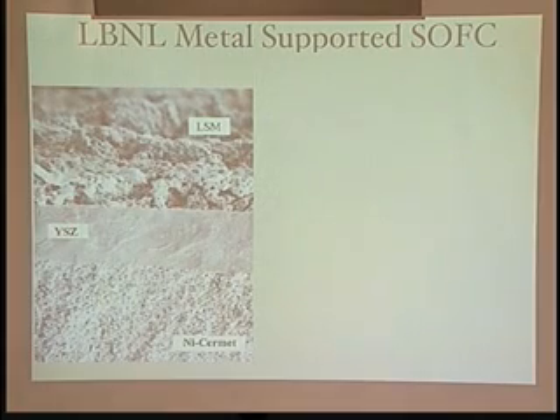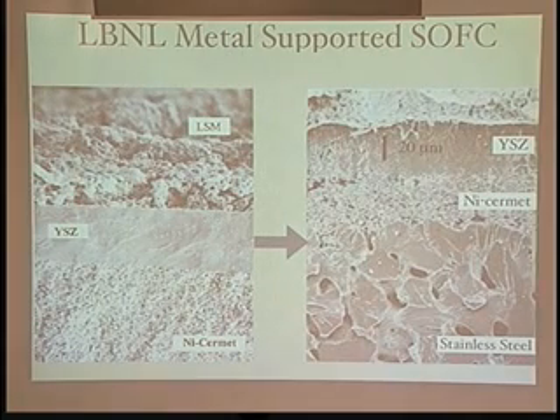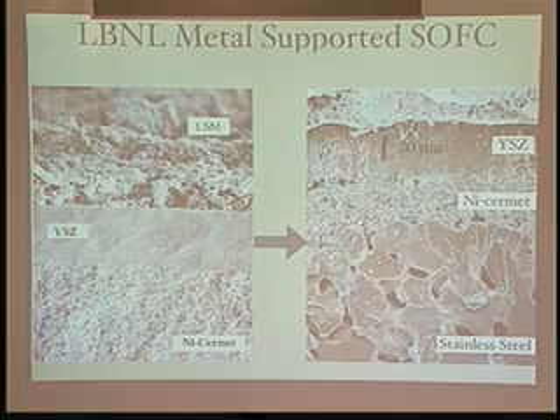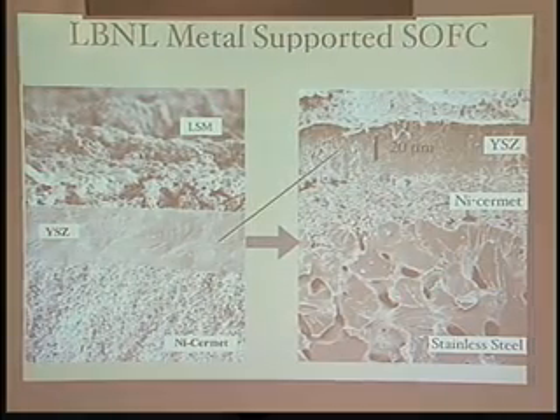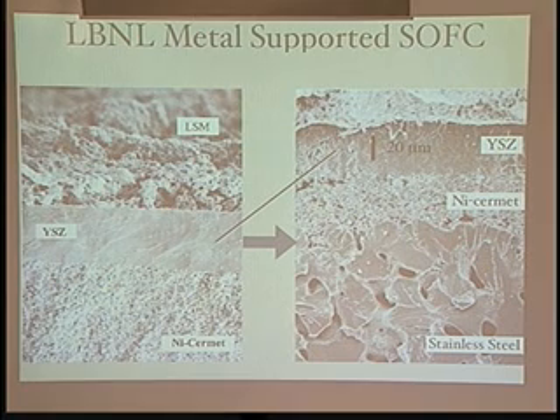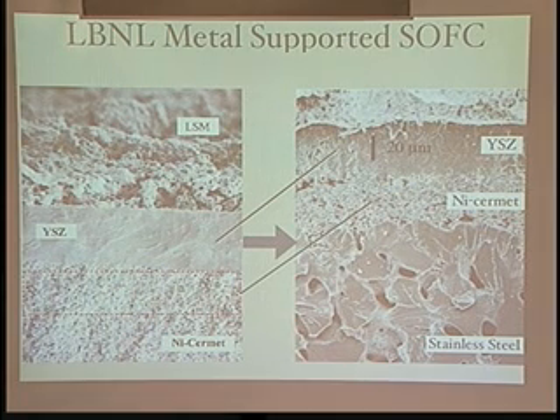And so what we had to do then is go from this structure to something like this. And of course we did it, because that's what you're seeing. So what it meant was replacing this. The zirconia film stays; that's the 20 micron zirconia film, a little thicker. But now this electrode, which was in fact millimeters thick, is now just a very small section of it, about another 20 microns, that will get put in between the steel and the zirconia. And so the bulk of that mechanical support here is replaced now by stainless steel.